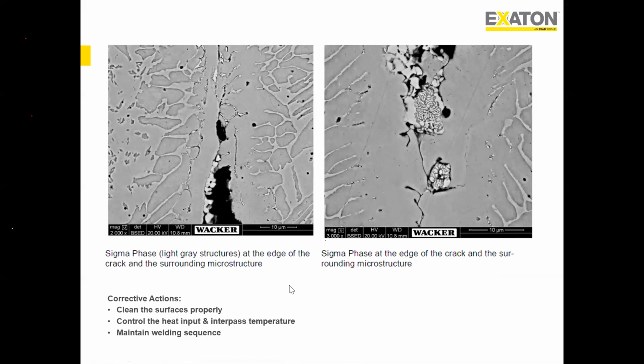And last, we also found sigma phase. You can see this is the sigma phase on the edge of the crack and the surrounding microstructure. So it is quite a detailed case study that we did. In summary, what we found, number one, what the mistake was. It was a 64 millimeter thick plate. When they did the fabrication in the yard, they forgot to clean the bevels properly.